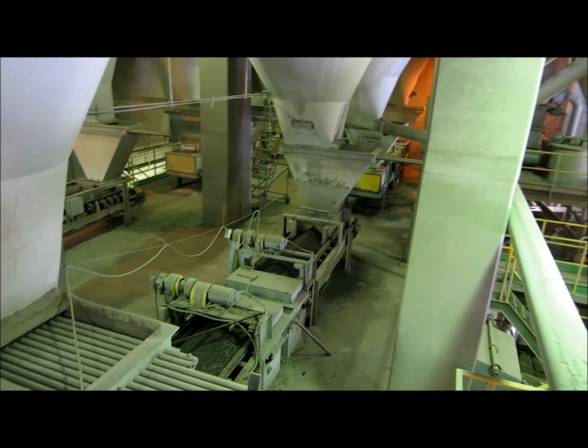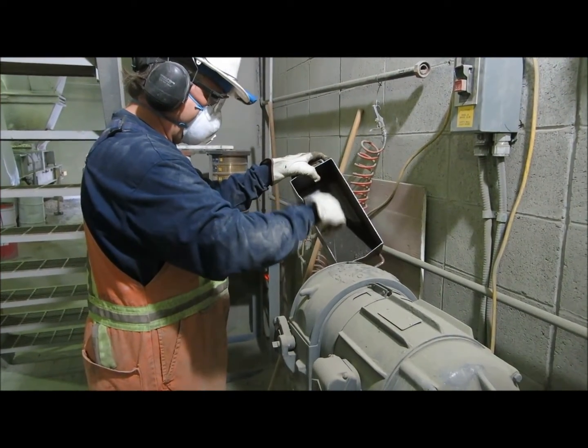The kiln feed chemical composition has a large effect on the clinker and the performance of the kiln. Variability in the raw material can make it very difficult to produce a consistent product. In an attempt to alleviate some of the variability in the raw materials, methods of pre-blending and selective mining are used. The chemistry of materials entering the raw mill are tested every 3 hours, and changes to the raw feed are instantly made with an automated system in the control room that is monitored 24 hours a day, 7 days a week.